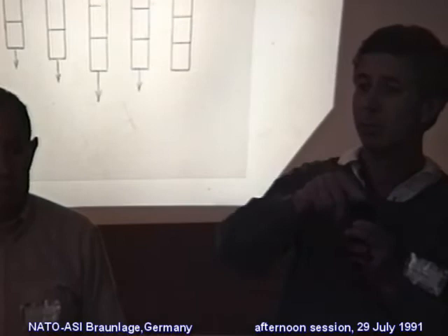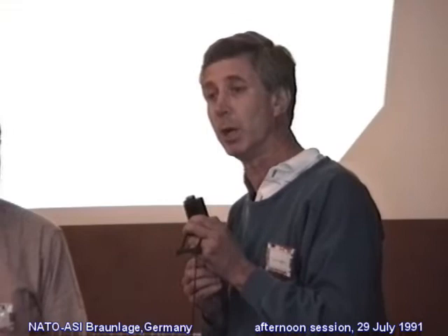And going forward and back, we have a kind of hysteresis. But in a state of thermal equilibrium, and we do this as slowly as we please, and if the energy barriers are quite large, this may take a long time, but in principle, at temperature greater than absolute zero, we ought to be able to come to a state of thermal equilibrium and satisfy a more general criterion of that kind. But if you really want to look at that, I commend you to read Rice's paper, 1978, and I can get you a reference to it.